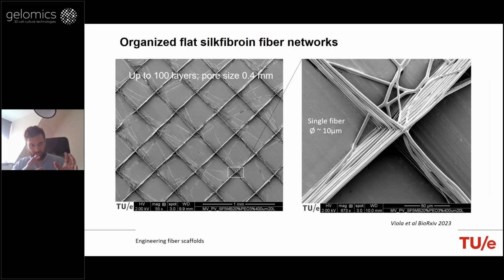In this case, we look at flat and tubular, and we could lay down silk fibers up to 100 layers. And typically the fibers had around 10 microns of diameter, and we could lay down with quite a good accuracy up to 100 layers in a controlled way.